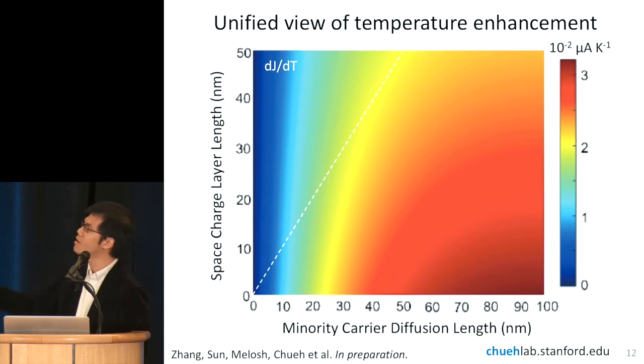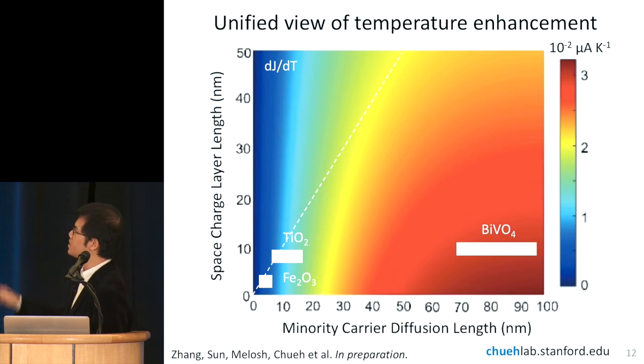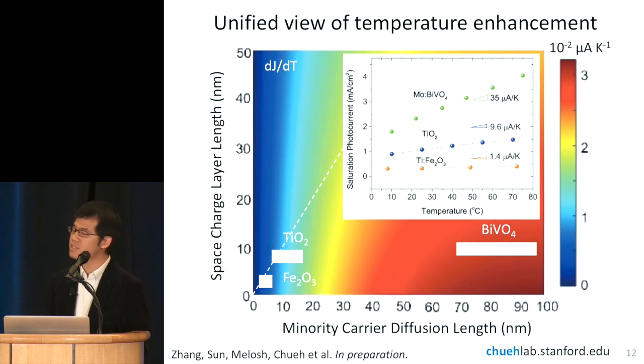So this is same diffusion length as the space charge layer. Iron oxide sits pretty much on the line. So that gives you a fairly low enhancement. Titania sits a little bit further to the right, which is good. That means more light is absorbed in the region that can be activated by heat. But bismuth vanadate sits far to the right because the minority carrier diffusion length is much longer than the space charge layer width. And this is consistent with our experimental observation that we have minimum enhancement for iron oxide, a little bit better enhancement for titania, and much better enhancement for bismuth vanadate.